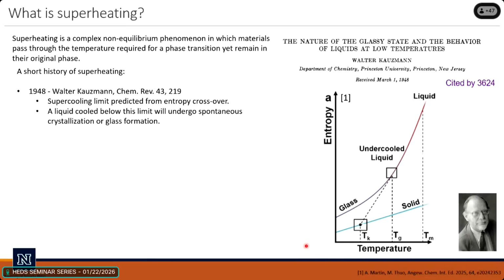It started way back in 1948. This guy, Walter Kauzmann, actually predicted a supercooling limit. He said, how much can I cool something down and it stay a liquid, so not freeze? And what he did was he took essentially the entropy of a liquid and the entropy of a solid, and he just went like this and extrapolated them down. And there was a point where they crossed. And he said, well, if you keep going, I'm going to get a solid with a higher entropy than a liquid. And that's weird. That can't exist. And he said that if that happens, you will get a spontaneous freezing into a glass transition, essentially. And he called this the Kauzmann temperature.